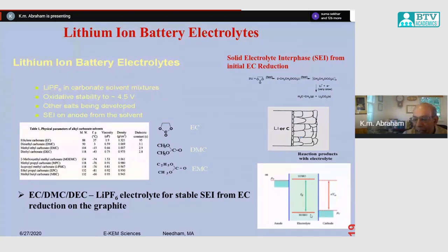Well, this shows that the band gap or the stability window of the electrolyte has to be better than, or outside of, the electrodes, because you don't want the electrolyte to reduce and oxidize when you charge and discharge your battery. So it's a very involved process to come up with a practical electrolyte. That's why sometimes the development of batteries takes a very long time.